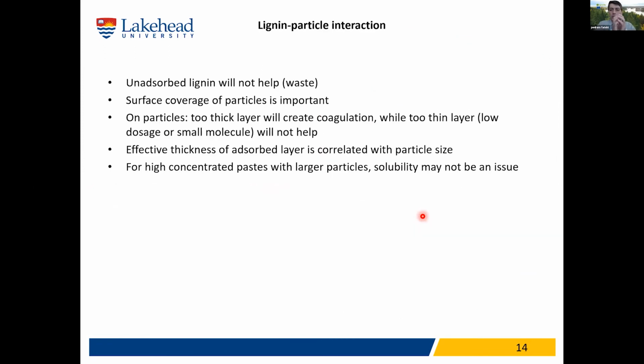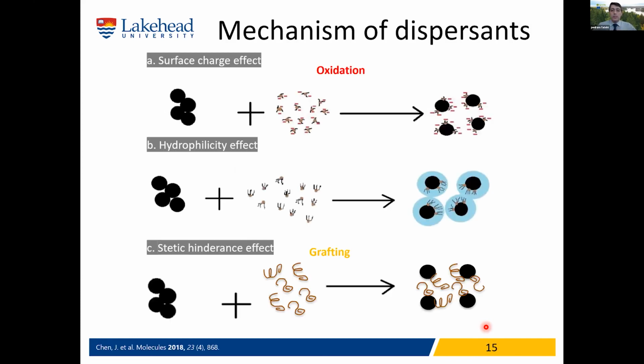So altogether, what we realized, and that's a very important aspect, is that the adsorption of whatever lignin-based dispersant you produce on the particle is very important, because unadsorbed dispersant that is available in the suspension doesn't function. So what matters is that adsorbed level. So surface coverage of the particles in the suspension is very important. So you need to design somehow to have a really good interaction. Too thick a layer of your lignin-based dispersant could cause coagulation instead of dispersion, and too thin a layer would not help. So that will affect how you design your lignin-based dispersant. And of course, the thickness will be a function of particle size. But the other thing is that I'm not sure if you need to have a soluble lignin or not for some applications. So these are the mechanisms of dispersion.